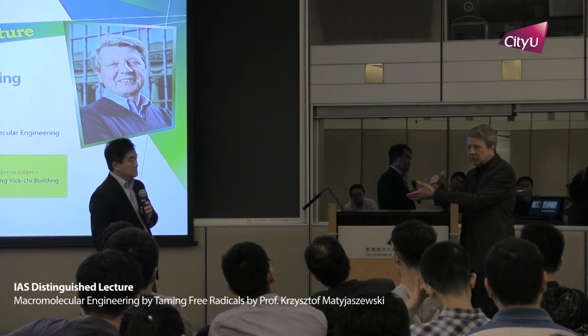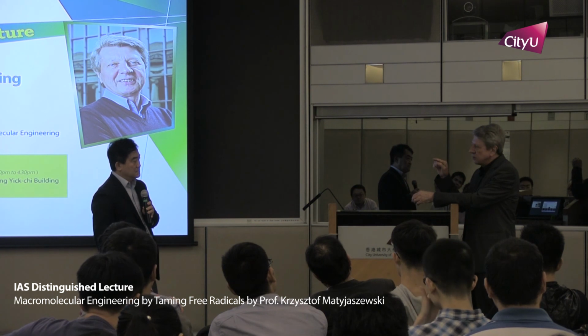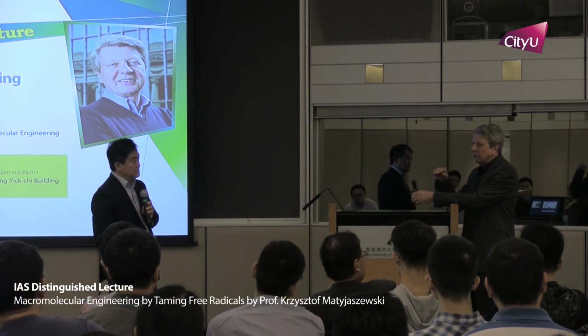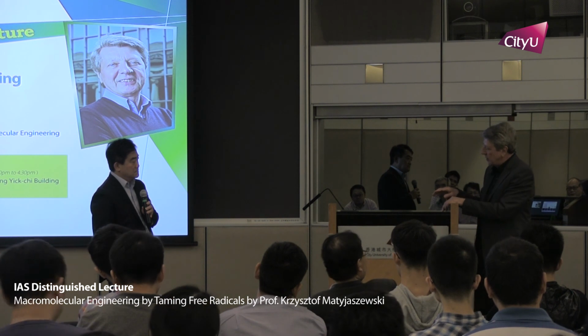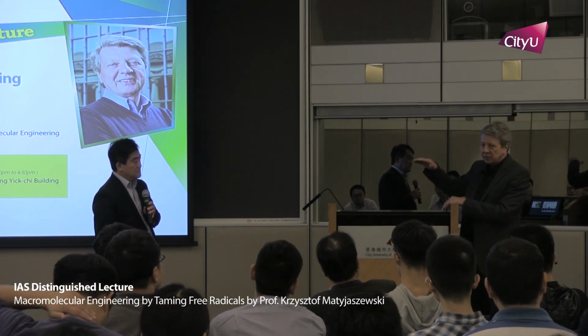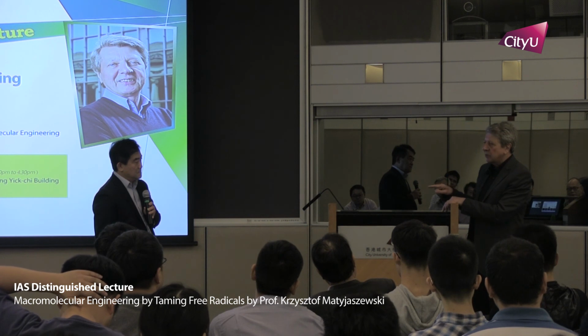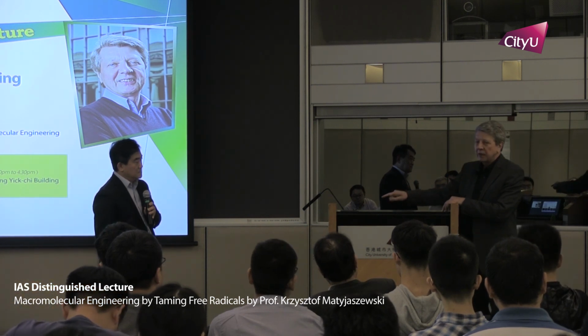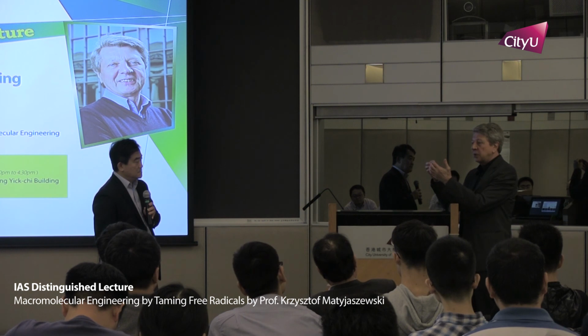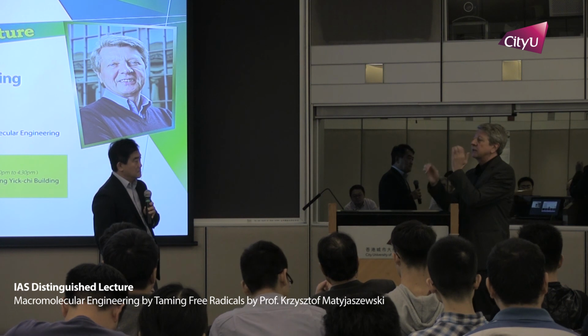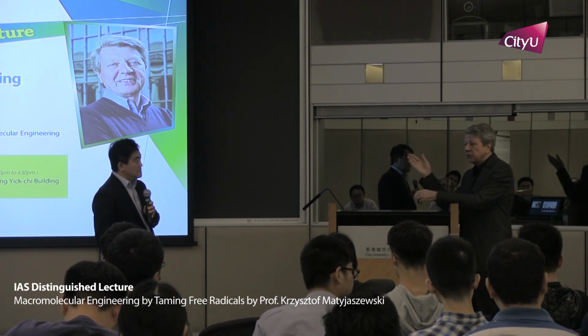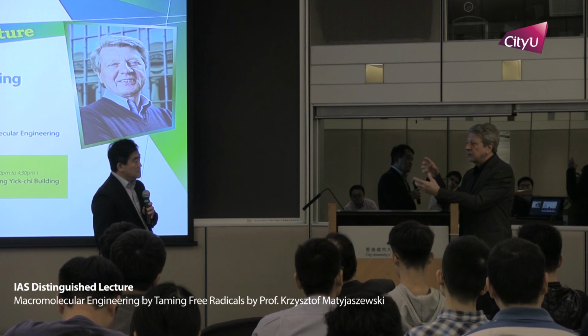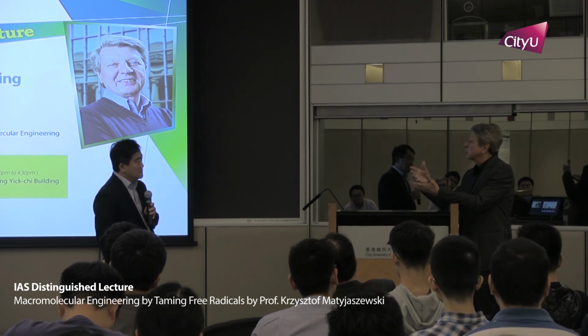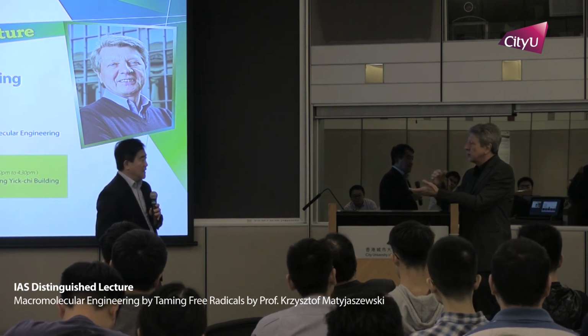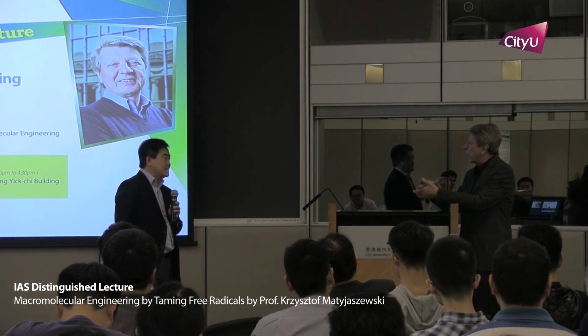We sometimes graft also from flat surfaces. In that case, it was Jacob Klein from the Weizmann Institute who made an experiment. He had a 1,000 kilograms load, and with a force of 1 gram, he could just push it on top of the other one. The reason is that if you have a very dense polymer brush, they cannot interpenetrate, they cannot entangle, they slide one on top of the other. This phosphorylcholine has an additional advantage that it is also highly water swellable, like an ionic system. So we have additional lubrication from the aqueous system.